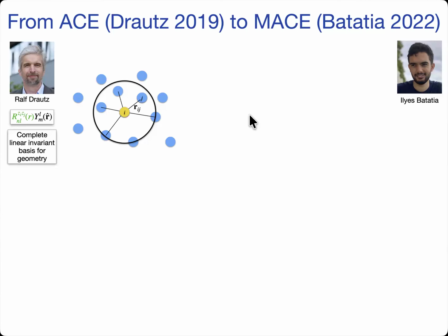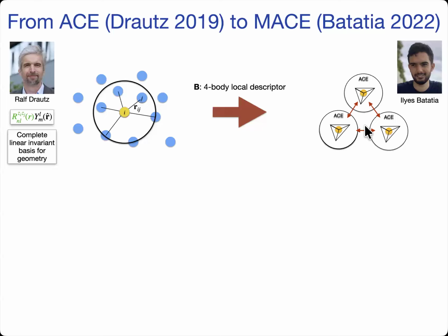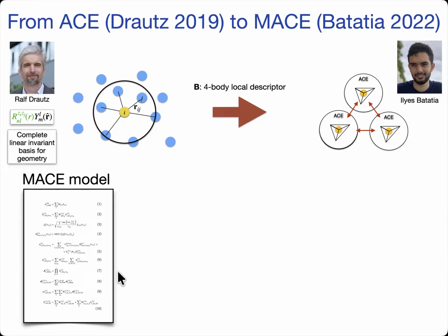We moved on in about 2022, mostly the work of my graduate student, Ilyes Batatia, who takes the local description in terms of a radial basis R and Y_lm of a neighborhood of an atom. We form 4-body descriptors. ACE in principle allows arbitrary body order, but it's enough to form these 4-body descriptors. You create these ACE descriptions around each atom, and then you pass that description around. Every atom hands the description to its neighbor. That's called message passing. And then you do it again. Then you re-expand those messages you receive in the 4-body truncated linear invariant basis. And that is essentially MACE.